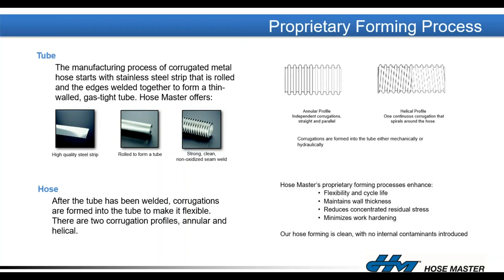We then take that strip of steel and form it into an airtight tube by doing a weld that is purged inside and out. That purging displaces the oxygen away from that metal during welding to minimize any oxidation of that seam weld. So it's very important that the seam weld, as well as all those fabrication, the fitting attachment welds, are all performed with fully purged welds in order to minimize oxidation, which makes that metal more vulnerable to fatigue and corrosion onset. So purging is a very vital part of metal hose fabrication, both in manufacturing the hose and fabricating the assemblies.